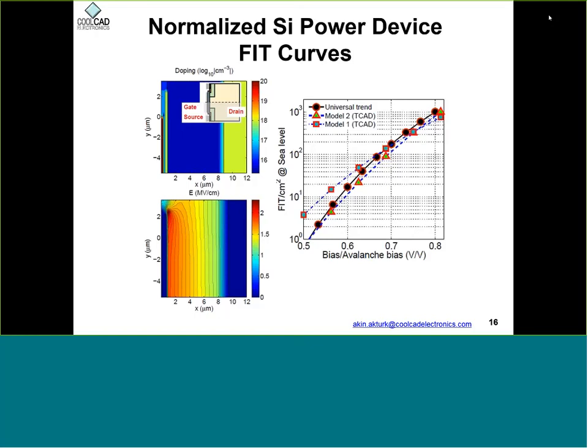So this is the first level, where you have a field-dependent failure rate, and after you get your regular field curves for a device in blocking state, you just run this post-process and it will tell you a failure rate as a function of position, which you can integrate to get the failure rate for the device.